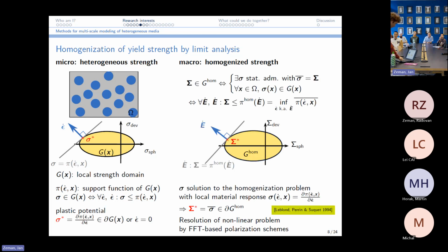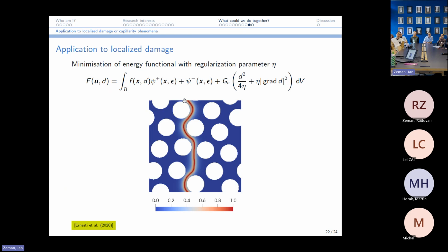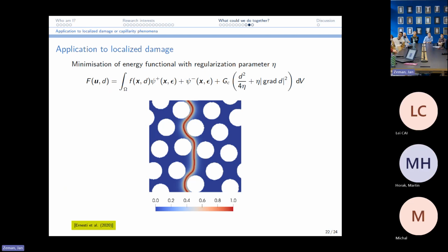And then about the last thing, the perspective I showed here, obviously at some point, if you have a localization, you have a through crack, you escape from this assumption of scale separation. But still, you could use that numerical method, not for homogenization purposes, but just for computing a structural response on a heterogeneous sample. And you could avoid this periodic boundary effect that forces the crack to end up where it started at the beginning, by putting a layer of pixels here, which is air, with no stiffness. Then you have free edges, and you can avoid this. You use this method, which was dedicated to homogenization, for other purposes. Or Ivana is considering some options for how to change the boundary condition. Oh, that would be very nice. Yeah, there are some papers on that, from a slightly different perspective, I do believe.